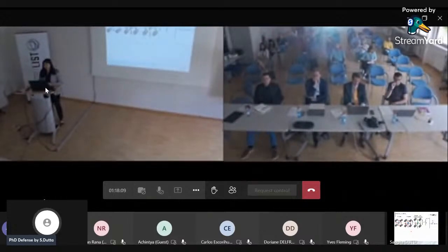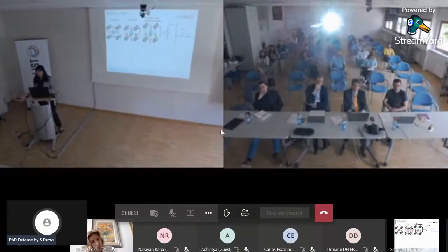To explain that, let me go back to lead titanate. Here this is the paraelectric phase, and these arrows represent how the atoms move from the paraelectric to the ferroelectric phase. As you can see, all the cations are going up and the anions are going down, so you get a polarization pointing upward. Now imagine you are stretching the structure along the vertical direction. The green arrows here represent how the atoms react to that stretch. As you can see, for example, if we focus on the titanium and oxygen, they have a short bond there.